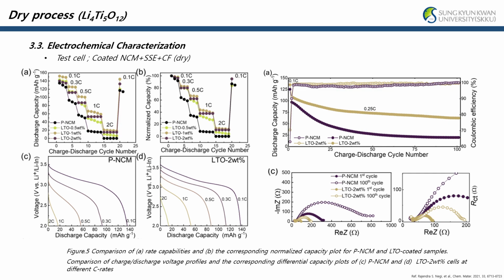characteristics of the coated cathode active material and pristine, it can be verified that the overall capacity fading is low. The characteristics at a high rate are improved, and the long-term life is also improved. In addition, the resistance was also very reduced, and it can be seen that the interfacial resistance by the oxidation reaction was effectively suppressed.